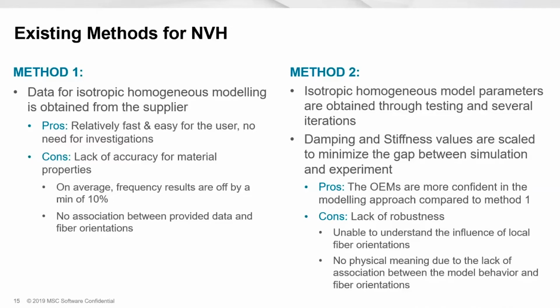So this method is good, and the OEMs can be more confident in the modeling approach as it's obtained from internal investigations. But the cons of this are, again, we're unable to understand the influence of local fiber orientations on the material's anisotropic stiffness and damping values. There is also lack of robustness. So the identified model is highly linked to the component, injection settings, and the load cases used for component testing.